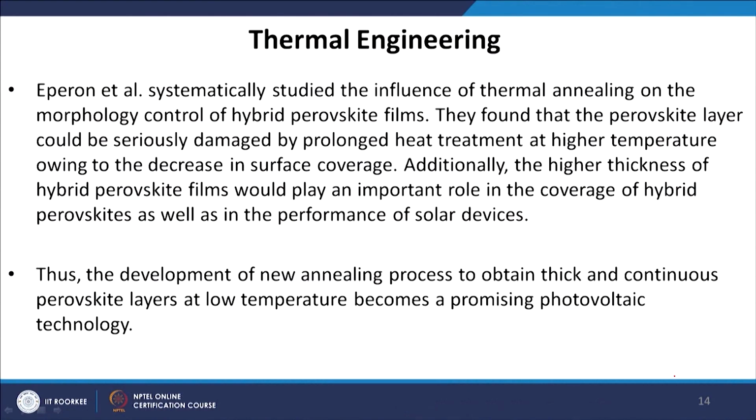Now, there are several groups which are working on thermal engineering. For example, Eperon's group systematically studied the influence of thermal annealing on the morphology control of the hybrid perovskite film. They found that the perovskite layer could be seriously damaged by prolonged heat treatment at high temperature owing to the decrease in surface coverage. So, for example, if you expose the perovskite film to a very high temperature for quite a long time, the film will be damaged.